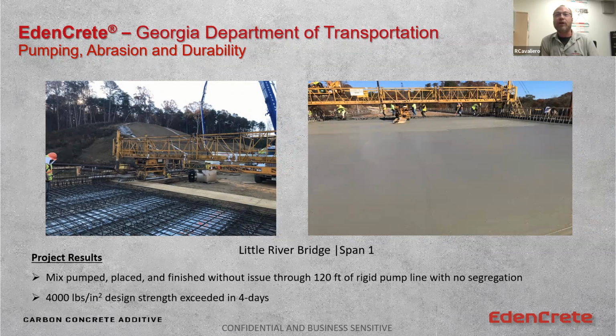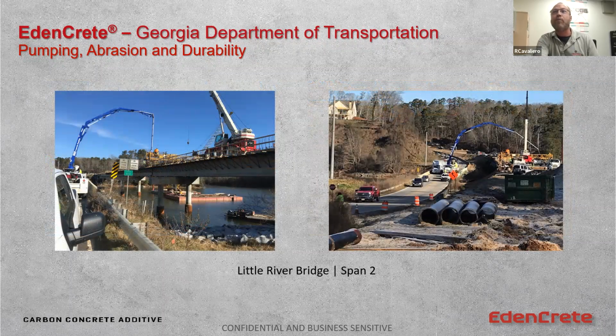Ultimately, the fresh properties that EdenCrete improves helped with the placement with this slip form paver to get the concrete down without adding water, and without having to add water to the surface, causing any problems with the ultimate durability. The other thing here is that this is how they poured span 2. This is span 2 poured 1 month after our span was poured. So 26 days after we achieved the design compressive strength. They're removing this bridge because it's structurally deficient. It doesn't seem like it makes sense to put the motoring public, traffic control, a concrete truck, and a concrete pump truck on top of a structurally deficient bridge to pump to a new bridge when your first span has already exceeded the design strength that's required for the bridge to open to service.